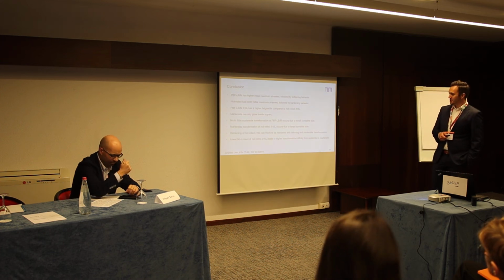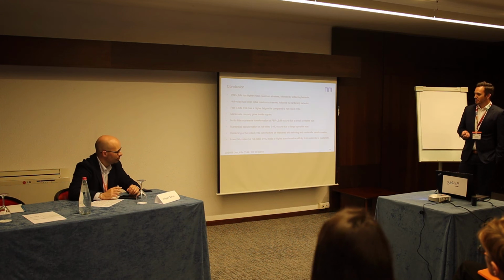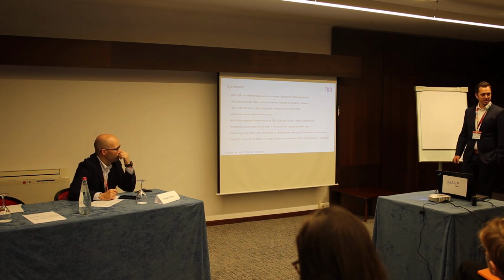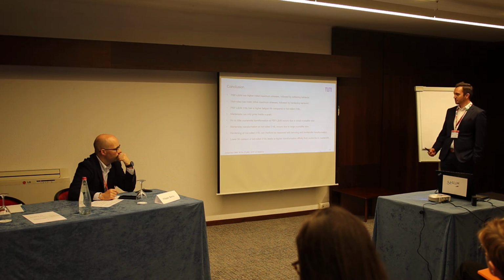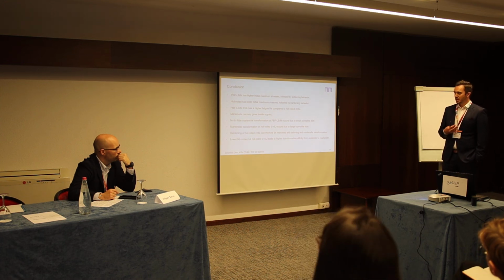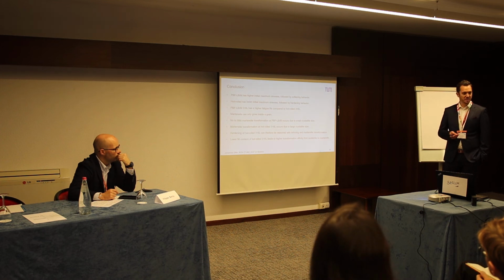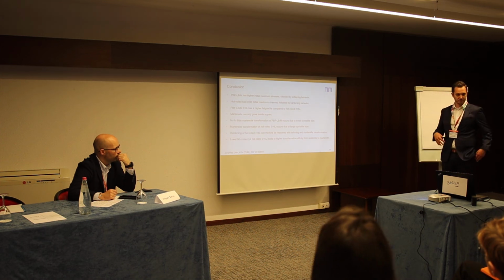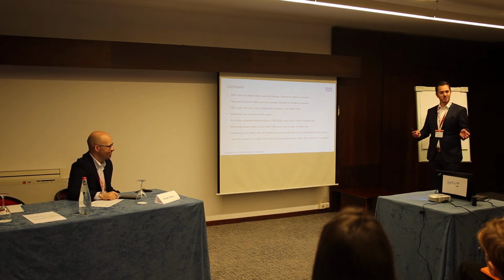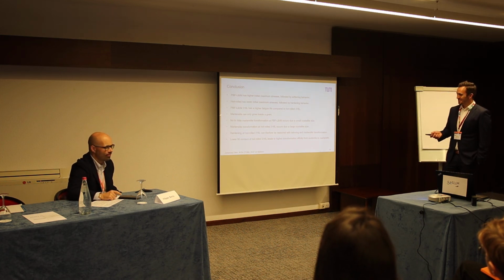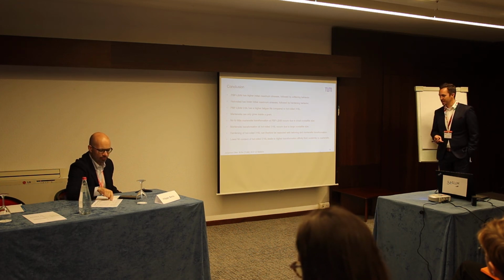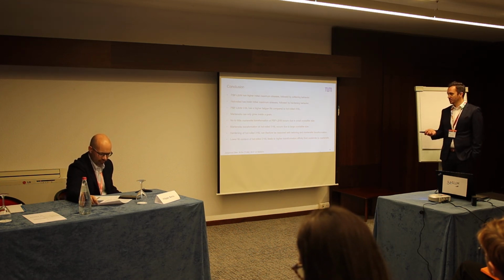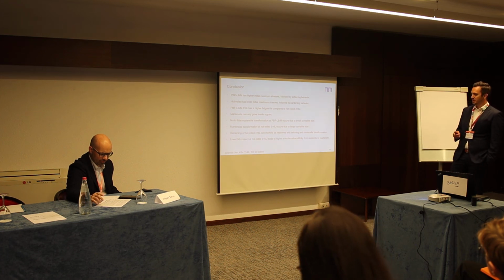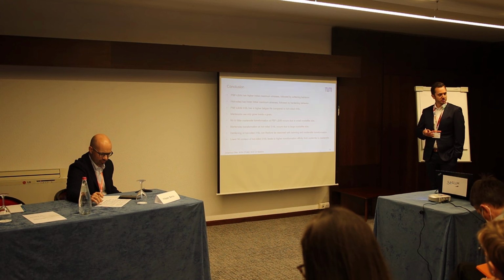So to get to the final conclusion, and I hope I still have some time, the PBF-LB has higher initial maximum stresses, followed by a softening behavior. Hot roll 316L has lower initial maximum stresses, followed by hardening behavior. And PBF-LB 316L basically has a higher fatigue life compared to hot roll 316L, at least for my results. I mean, I need to do more to actually state that properly. As I said before, martensite can grow only inside a grain, and therefore we are thinking that too little martensite transformation occurs in the PBF-LB manufactured 316L due to the small crystallite size.